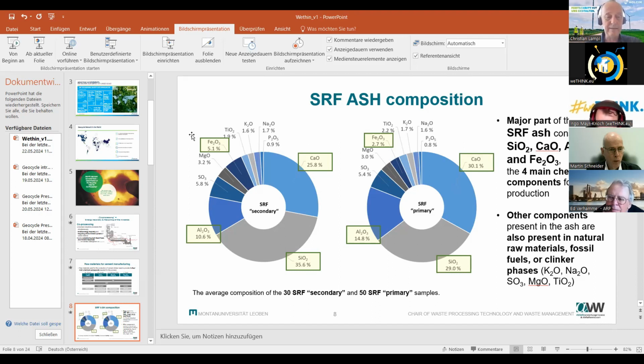This is the result of the ash composition of 30 calciner fuels and 50 main burner fuels. And as you can see, the main components are again calcium oxide, silica oxide, aluminum oxide, iron oxide. These are the main components, and this should show that this is really material recycling.